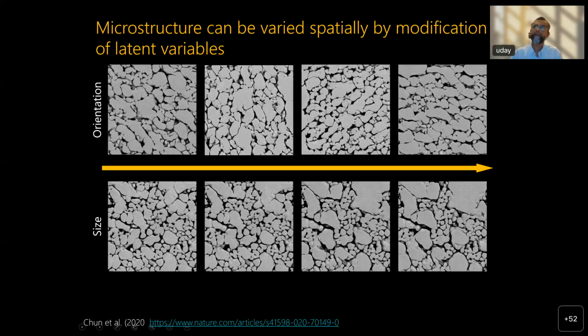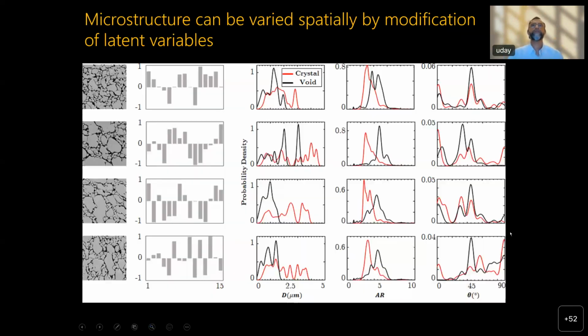We can also look at mixtures of sizes by modulating the latent variables. The uniformity, if we toggle the latent variables in a certain way, we get bimodal mixtures and so on and so forth. So we can now control the microstructures virtually. And these are a picture of the latent variable weights here. For different weights of the latent variables, we get different crystal sizes, void sizes, and so this allows for flexibility in making different microstructures.